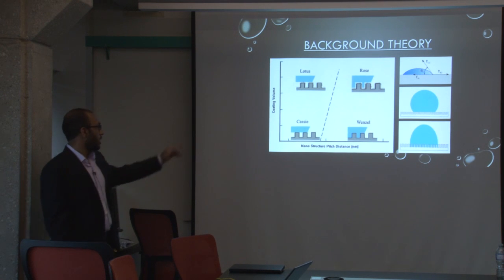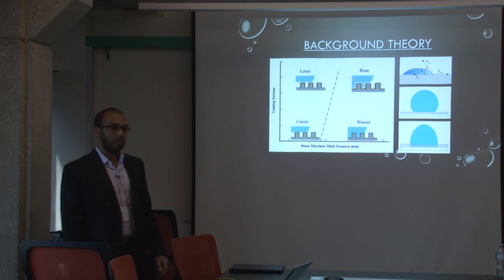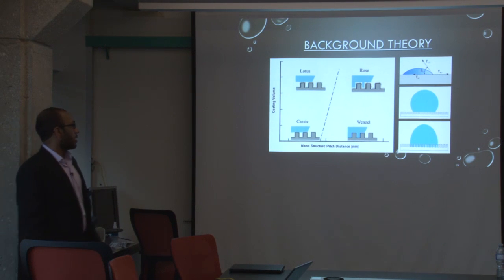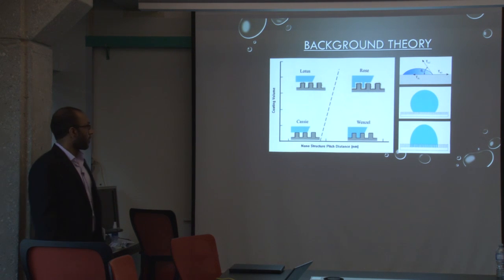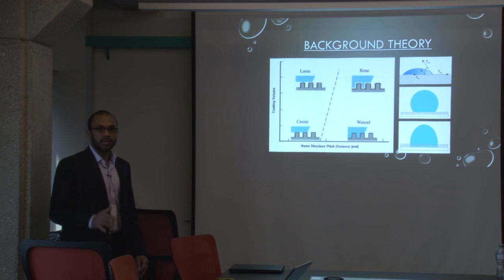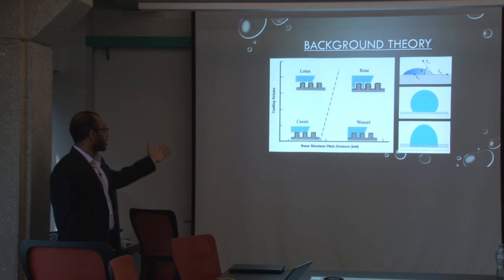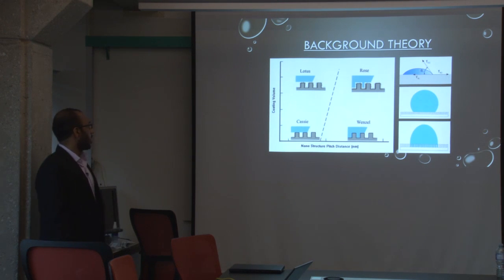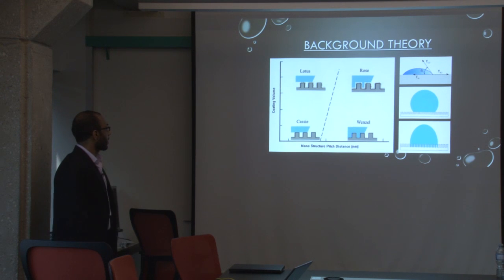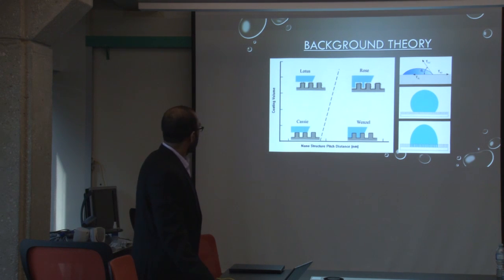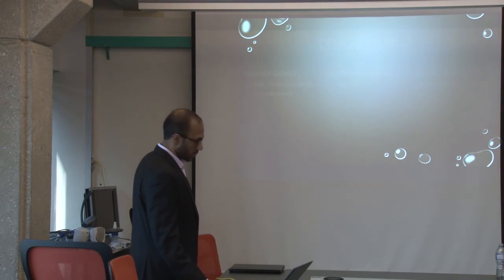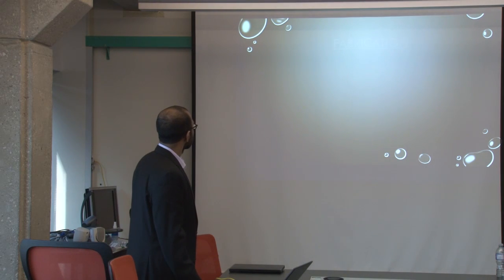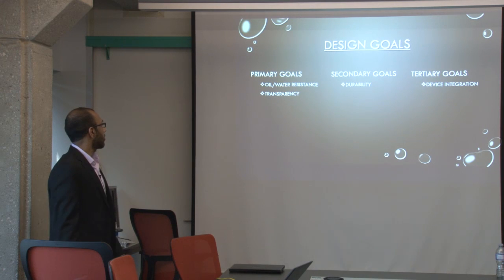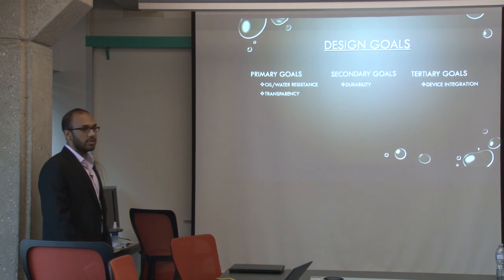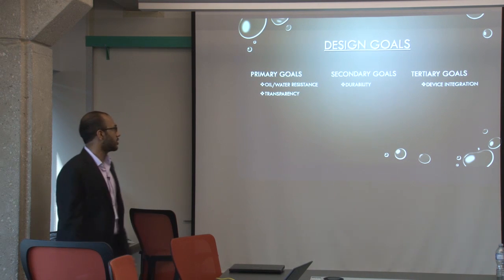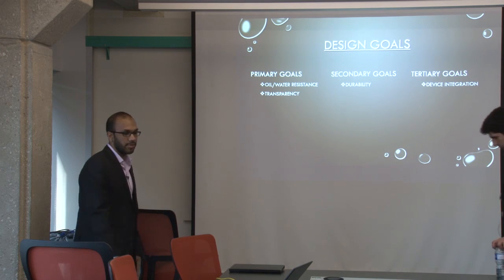And in the Wenzel state, the fluid penetrates in between the microstructures, and the contact angle is lower. And that, even though it gives some degree of hydrophobicity or oleophobicity, is not the maximum achievable. And there's a critical pitch distance, or the distance between the pillars, where you transition from one state to the other. So our design goals are to have an oil-water repellency that is transparent and durable for the usage of the device, and ultimately potentially integrated into the device as well. Now I'll pass it on to Saeed to talk about the fabrication.